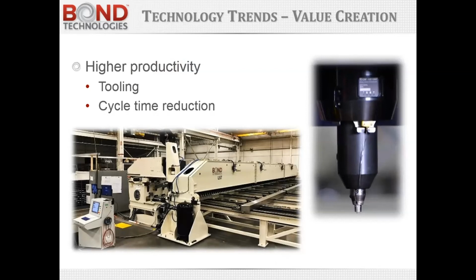One of the ways to improve productivity, at least to improve the development cycle, to find a process window that works for a given application, is to measure temperature of the pin tool as it's doing the weld. We also have the ability to close the loop and control to a constant temperature. And that can provide some great benefits in certain applications. The machine on the left is used for long panel extrusion.